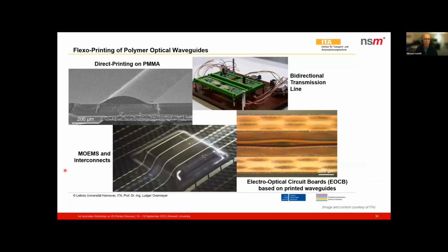This slide shows a project from our partners at ITA, Leibniz University in Hanover, Germany. All these results were also achieved using the Challenger with flexographic printing of polymer optical waveguides. On the top left, you see an optical waveguide directly printed on a PMMA substrate. It was built up in 15 layers of UV polymer using flexographic kiss printing. Thanks to the precise control of the Challenger 650, the printing height can be adjusted in 1 micrometer steps via software, layer by layer, if needed. That means each new layer makes contact only with the previous printed layer, but not with the substrate.